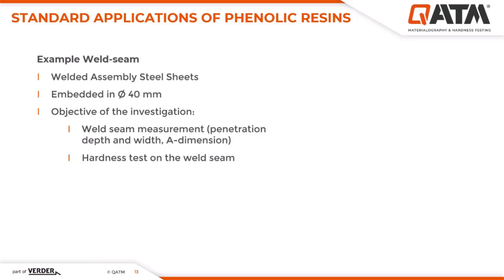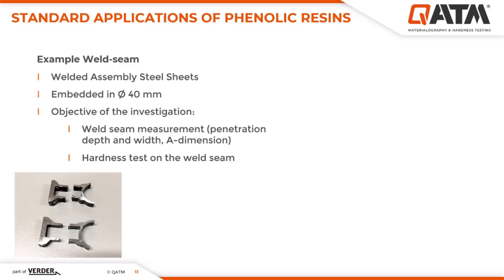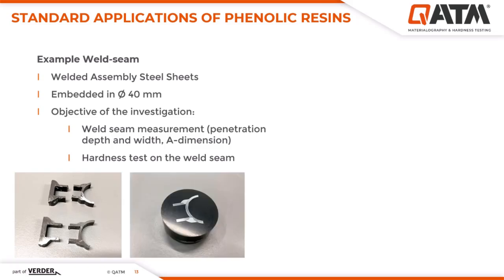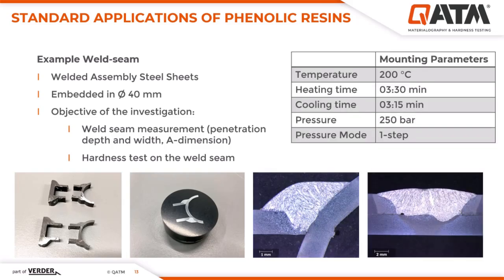In the second application example, I present a classic weld seam. On this weld seam, both a hardness test and the usual measurements were performed, including penetration depth, penetration width, and the A dimension. After cutting, deburring, and cleaning the sample, it was mounted in black bakelite. Mounting was carried out with a maximum temperature of 200 degrees, with a heating time of 3.5 minutes and a cooling time of 3 minutes and 15 seconds, and a pressure of 250 bar.